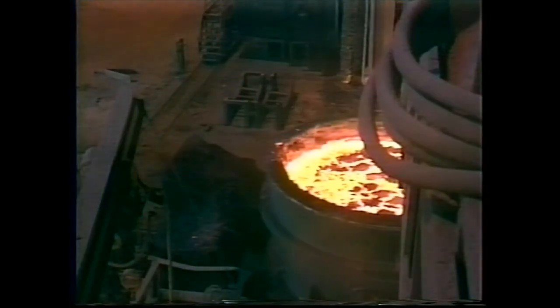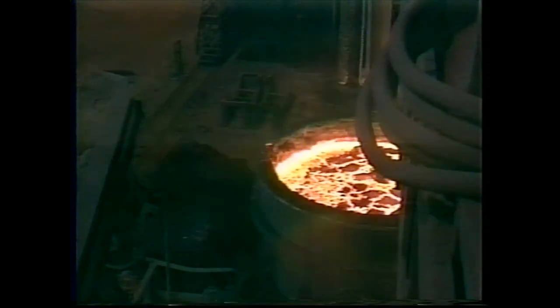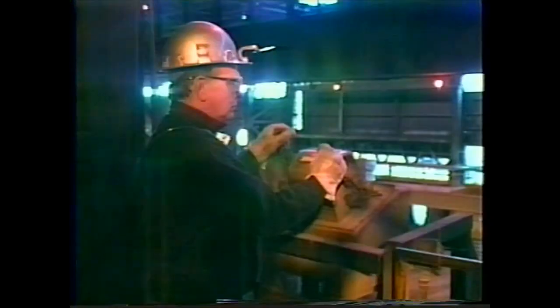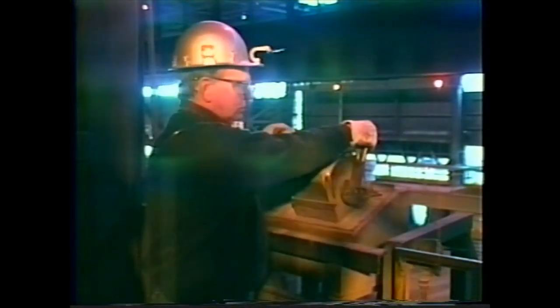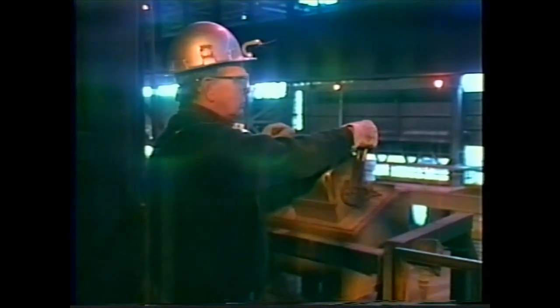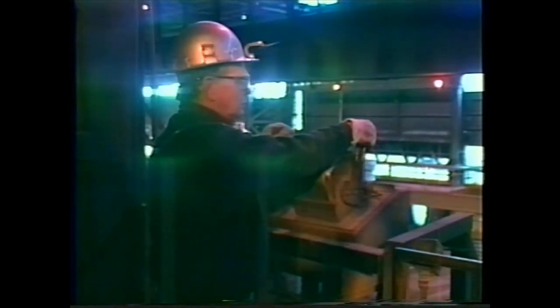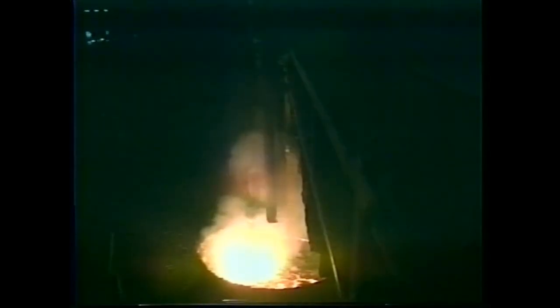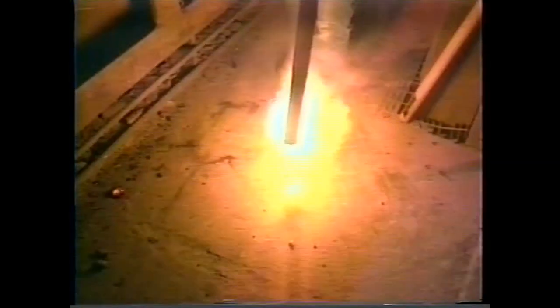The molten steel ladle on the ladle car is moved by the furnace man to the stir station. Here, the second furnace man stirs the heat by bubbling argon gas into the ladle. This provides a more uniform chemistry and temperature in the steel. He then takes a steel temperature and sample. This sample is sent to the BOF chem lab for analysis.